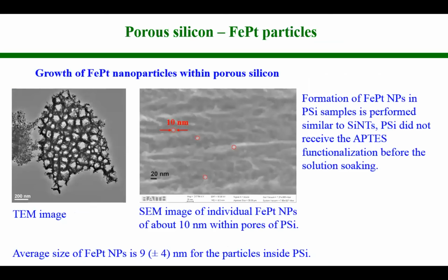So this iron platinum has also been done within porous silicon, and in this case, the formation is similar. The only thing is that the porous silicon did not receive the APTES functionalization. And here you see a TEM image and an SEM image showing the particles inside the pores. And here you see individual particles with an average diameter of 10 nanometers.